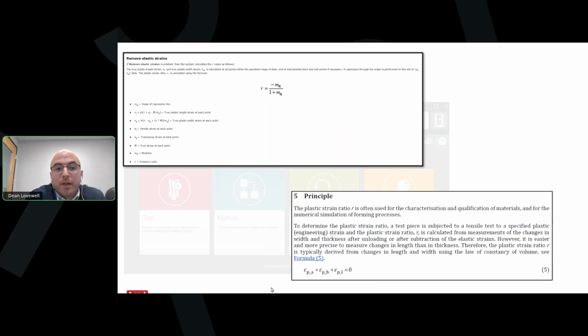One key area addressed in the help file is the question of elastic strain. As both ISO and ASTM require that we remove elastic strains in the determination of R value. This is really important because, as I mentioned, this is the same tensile test where we're determining tensile strength and elongation. So we're also expecting the test to proceed beyond the range where R value can be determined. This means that we need to automatically subtract these elastic strains during the test. Now, when creating a method with a template R value, this is automatically factored into the calculation.